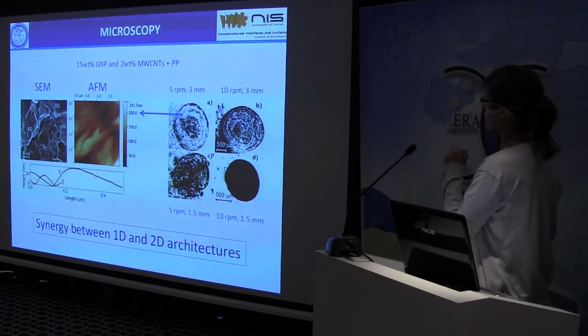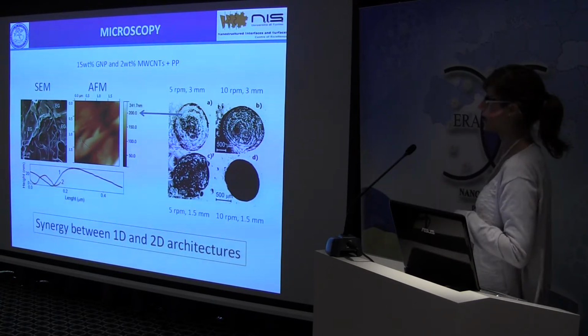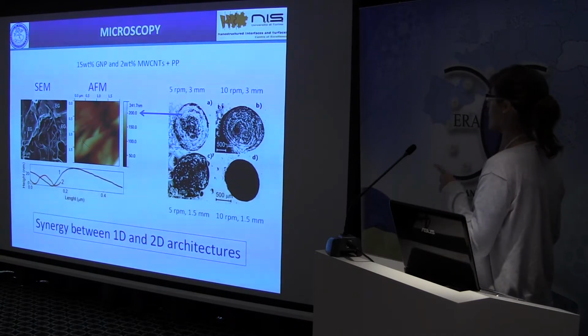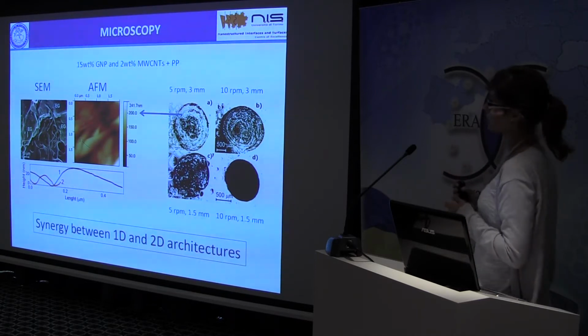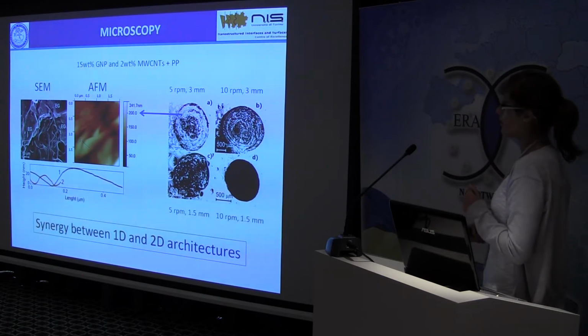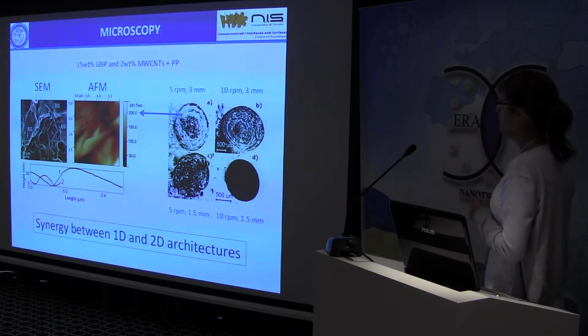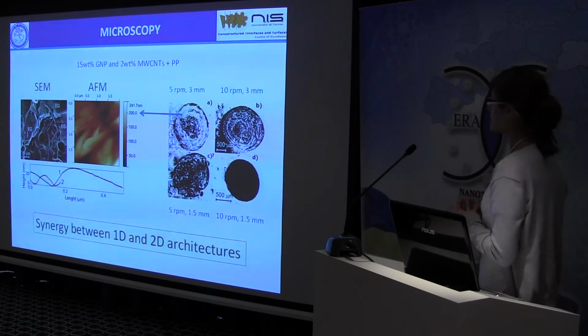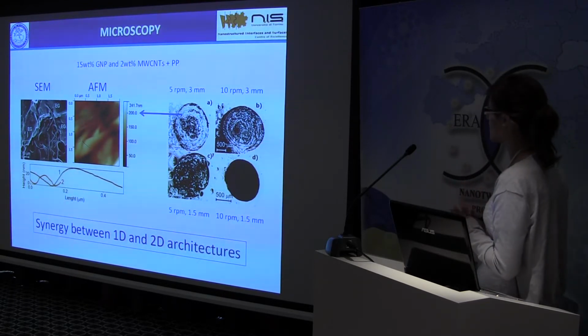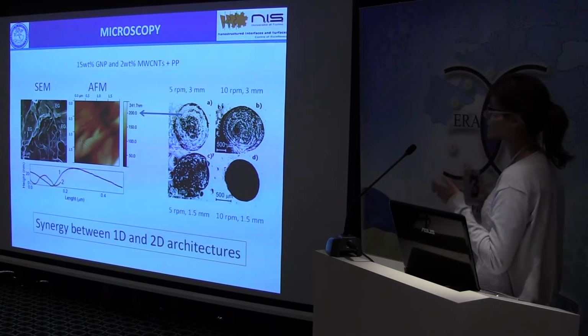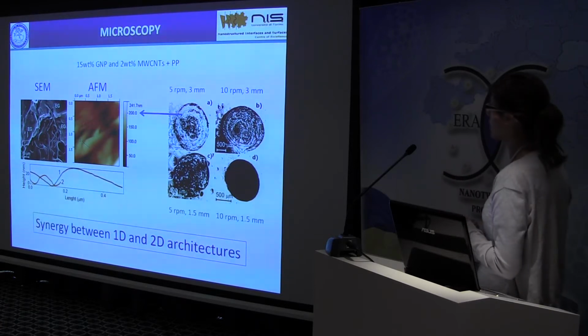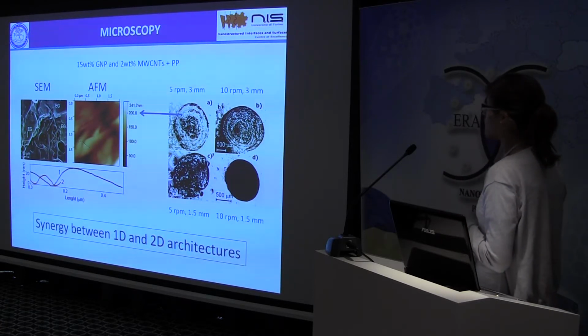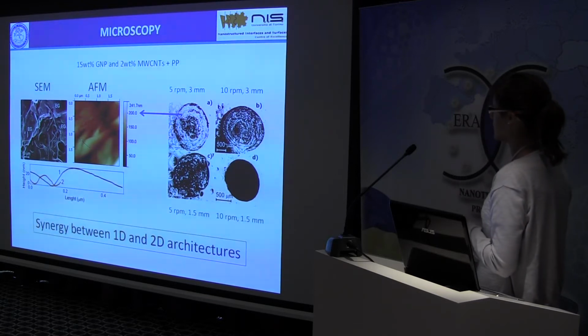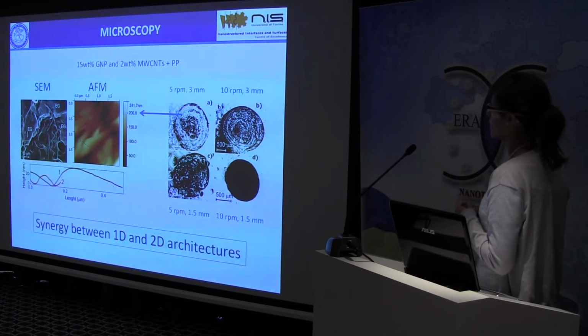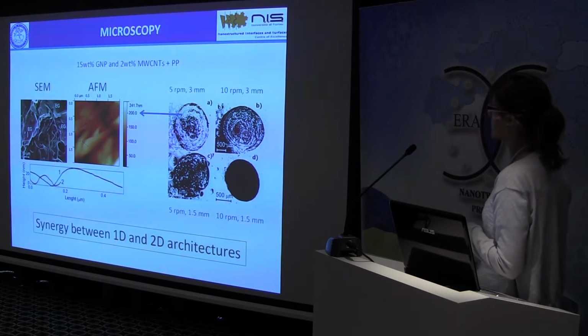Here, bright areas correspond to conductive areas of the samples, while dark areas correspond to non-conductive areas of the sample. And so we can say that we have obtained conductivity maps of our samples. With these images we can see the distribution of the conductive fillers within the matrix.